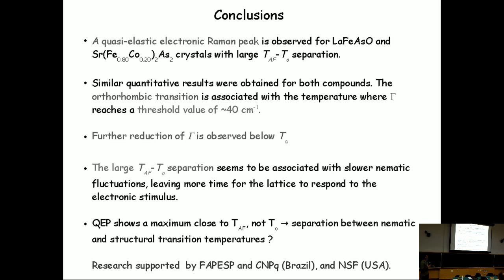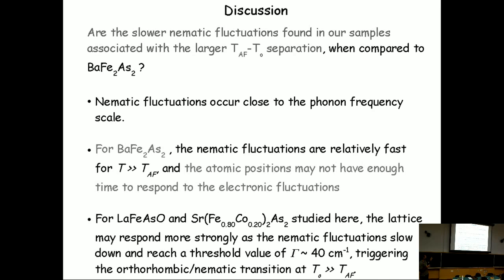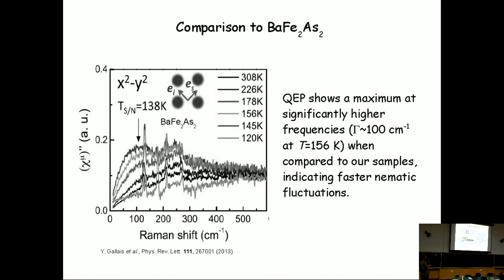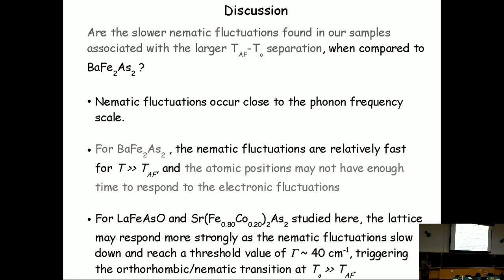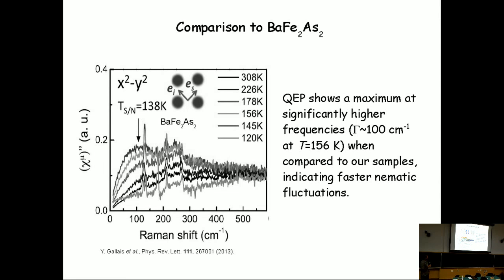In the previous slide, you have an additional peak at 120 Kelvin. Where is it coming from? That in gray. Okay, so these are data from Gallais et al. for the undoped system. These extra peaks are phonons. No, the one in the middle that is not in the higher temperature. Yeah, that one. So this is a phonon that's not allowed for the tetragonal phase, and in the orthorhombic phase it becomes Raman allowed in this geometry of B2G polarization. So that's a phonon that should not be there in the tetragonal phase, but by symmetry it's allowed to be there in the orthorhombic phase.